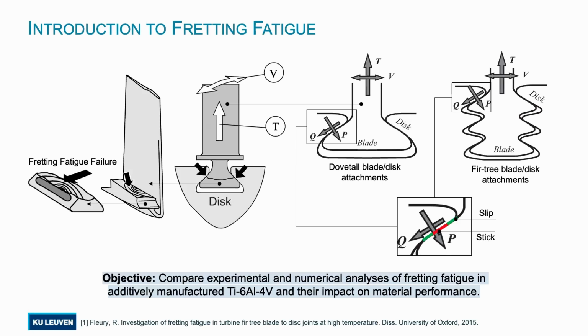Fretting fatigue happens in many applications, bolted connections, riveted connections. But in this particular application, we have blades. It could be a dovetail shaped blade or a fir tree, let's say, blade-disc attachment. At the contact interface between the blade and the disc, because of the two loading conditions that we have, tensile load and vibration, we get some local stress distributions. For both cases, this local stress distribution causes a contact load and also a shear load.